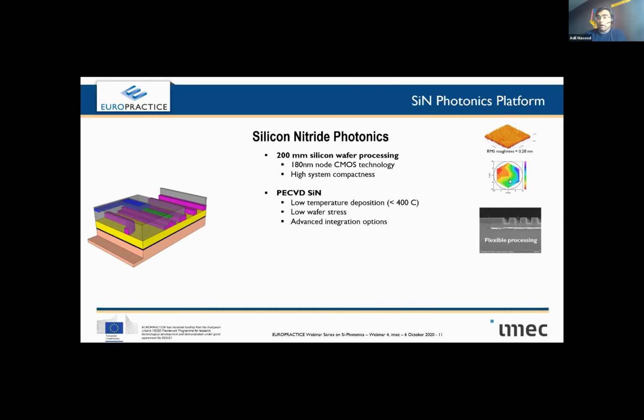Let me elaborate. Now, what's the thermal budget? At what temperature are you depositing this silicon nitride? If it's a process which requires very high temperature, that means whatever you have fabricated before silicon nitride on your stack will probably be wasted and will not perform very well. That puts a thermal budget. So a low temperature silicon nitride deposition gives you more flexibility to deposit layers over layers and keep patterning. But then, of course, there is a trade-off in the quality of silicon nitride, its propagation loss, and reliability. So these are the trade-offs which you have to work on. At Imec, the silicon nitride photonics platform is based on many different kinds of silicon nitride deposition processes, but the one which is available through MPW offers is based on PECVD silicon nitride deposition.